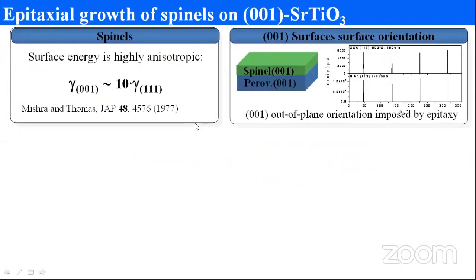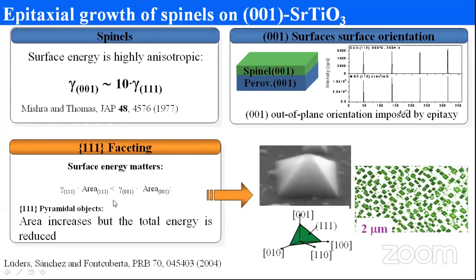Okay, in this slide, I'm going to show how a spinel structure, cobalt ferrite, we all know that's a spinel structure, grows on a perovskite 001 substrate. The surface energy of a spinel is highly anisotropic between 001 and 111. The 001 oriented surface energy is almost 10 times that of 111. So this surface energy matters for the growth. The surface energy and the surface area make this spinel structure grow as a pyramidal structure on a 001 oriented substrate.